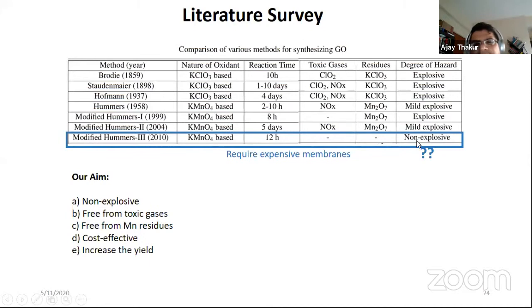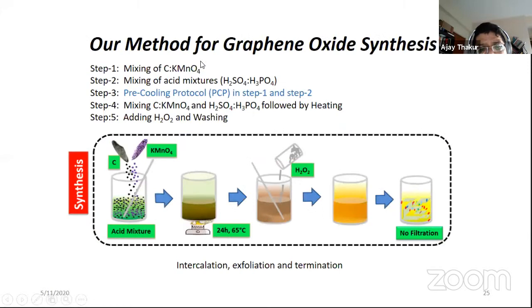Whereas whenever we try to replicate it in lab, it will always be explosive in character. And once we were in the process of publishing our result, indeed Tour's group also came up with a correction that indeed their process was explosive in the manner it was reported. So therefore, for us, it was a challenge to make sure that this explosive character in Tour's method is also removed. And what we did was we utilized a pre-cooling protocol in the initial steps of this reaction.